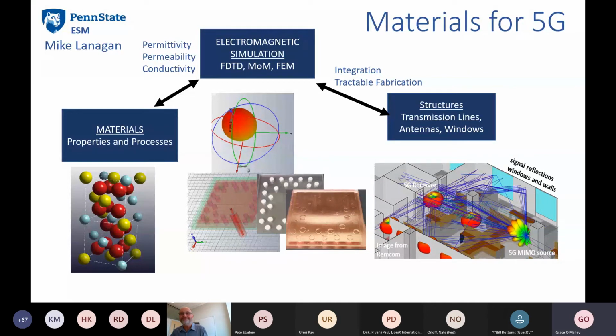Thank you. And then another was, could you please speak more to the thin films you showed in the plot at the beginning of your talk? So thin films have their own challenges to measuring the permittivity and loss. Because they're on a substrate, you have to figure out a way to remove the substrate contribution to actually get at the measurement of the properties for the film. There's a variety of ways to do that. One way is that we use the split cavity to back out the substrate permittivity, and then we deposit films to look at the difference between the substrate permittivity and the film permittivity. That's in terms of measurements, I believe, if they're asking about dielectric materials.